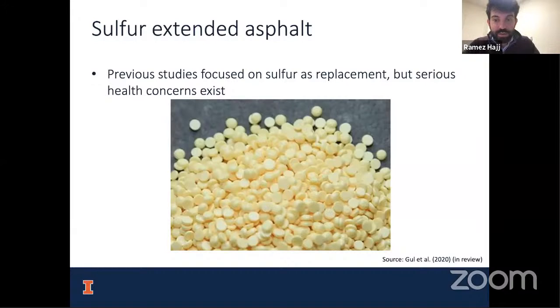So if we want to mix raw elemental sulfur into asphalt mixtures, we have to use a lower mixing and compaction temperature. In this study, we applied a mixing and compaction temperature of 140 Celsius, just tried to bring it down 10 degrees first. We noticed this decreases a lot the amount of hazardous chemicals, or hazardous emissions.